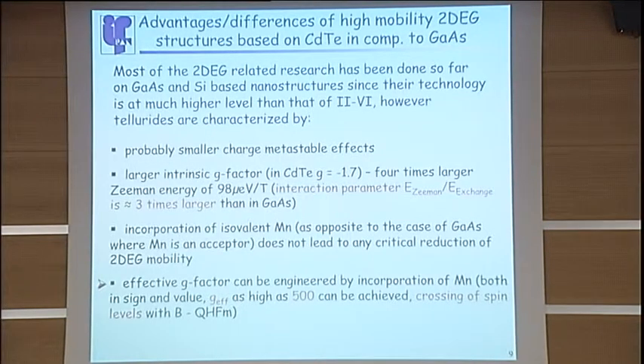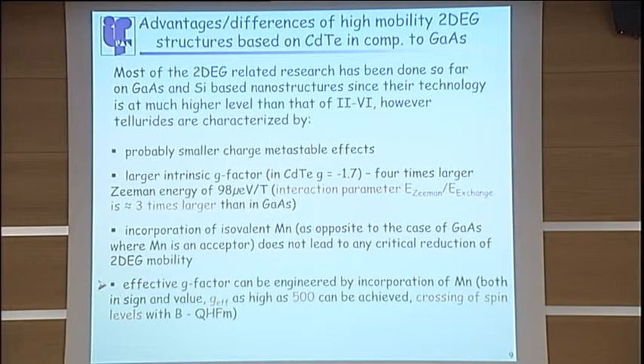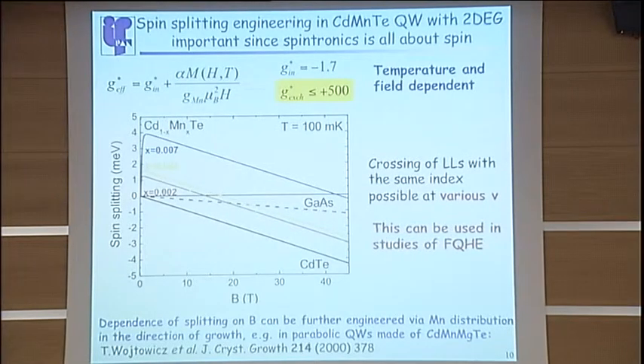For instance, in cadmium telluride, the g factor is minus 1.7, which gives 4 times larger Zeeman energy. Now, incorporation of isovalent manganese, as I already told you, as opposed to the case of manganese in gallium arsenide, where it is an acceptor, does not lead to any critical reduction of the mobility. And finally, the most important part, you can engineer the effective g factor in these materials, and this g factor can be made both negative and positive, and an effective g factor as large as 500 can be reached. Also the spin splitting can be engineered so that you can have the crossing of spin up and spin down levels at any required value of the magnetic field.